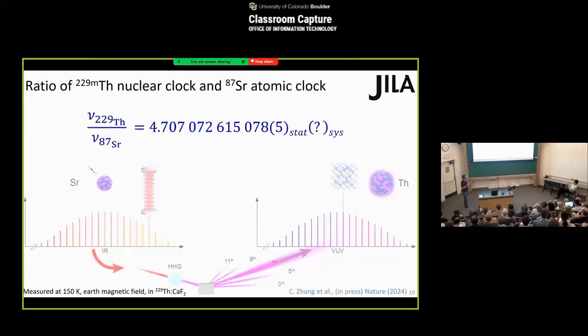So now with that, we can also report a frequency ratio between the thorium-229 nuclear transition and our strontium optical clock. This frequency ratio is measured with uncertainty on the 13th digit. We haven't evaluated the systematic uncertainty in this work, but in this work we are taking the data at 150 Kelvin, in Earth magnetic field, in a thorium-doped fluoride crystal. We care about this kind of frequency ratio measurement because essentially we are getting a unitless number that doesn't depend on our choice of frequency or time units. And this is a direct measure of how strong transitions that depend on the strong force and Coulomb force are, compared to atomic transitions that mostly depend on Coulomb forces. So this would give us a lot of insight for fundamental physics.